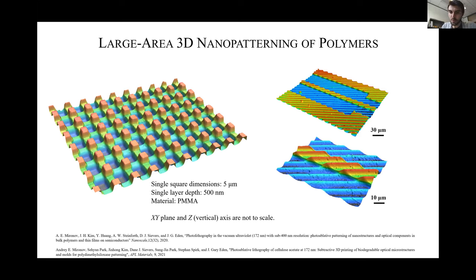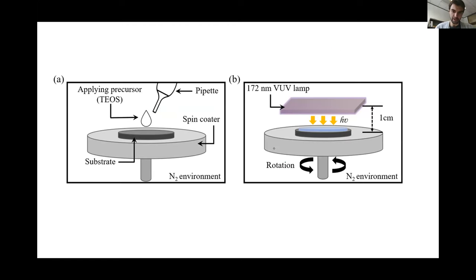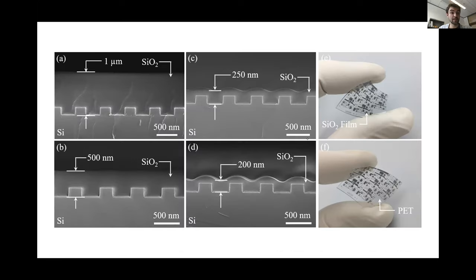So this is one of the applications, but I think one of the most important applications that we've discovered is the deposition of SiO2 from liquid TEOS. So the process is pretty straightforward. We use TEOS, spin coated on a sample, and illuminated with 172 nanometer light. And what you are able to produce is really high quality SiO2 films, having thickness from, I think the lowest we had was 30 nanometers, up to 1 micron at room temperature. So this process takes approximately 10 minutes or so to produce high quality SiO2 film on the entire wafer.